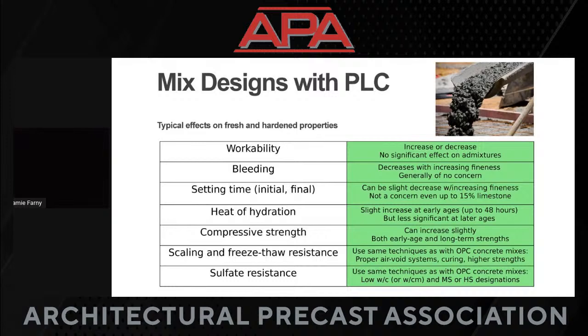So if we look at then the typical effects on the fresh and hardened concrete properties when we put PLC in instead of Portland cement, we look at the fresh properties like workability, bleeding, setting time, heat of hydration. If you're doing very massive things, that can be a consideration. We look at the hardened properties like compressive strength and our scaling or freeze-thaw resistance and our sulfate resistance. So in every case, we can see maybe a slight increase or a slight decrease, but not a big impact on any of these. And the reason, again, is we're talking about very similar cement chemistry. These cements set and harden the same way that a Portland cement does. They are largely Portland cement based.